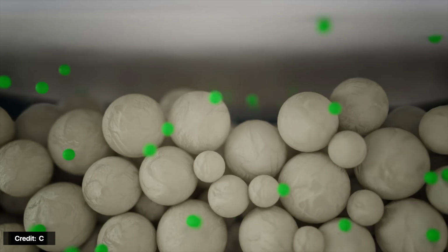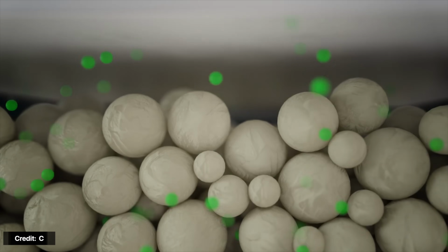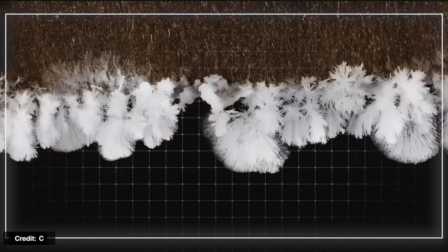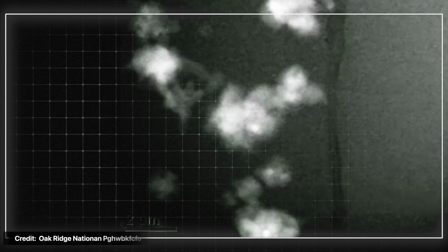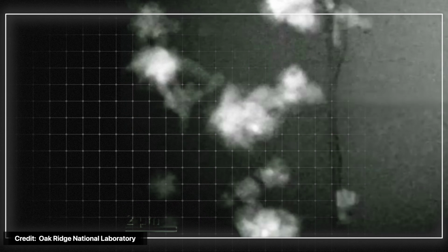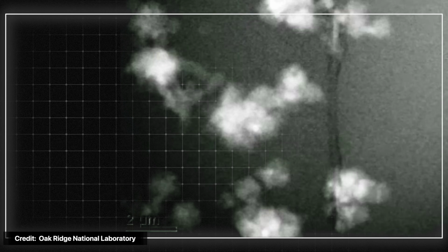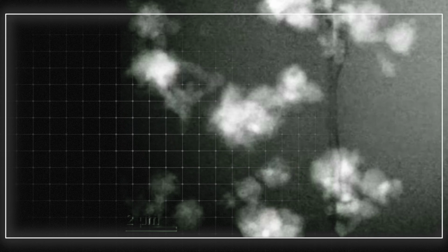One of the things that we've worked quite hard on is to understand why solid-state batteries typically require pressure and to design an architecture and a material system that doesn't require that high pressure. But here's the trap. When you apply pressure to lithium metal, it grows these tiny needle-like structures called dendrites. They're like little spears that punch through the battery and short-circuit the whole thing. More pressure means better contact, but more dendrites. Less pressure means fewer dendrites, but worse contact. And this is the death spiral. And it's why everyone said solid-state batteries were impossible.